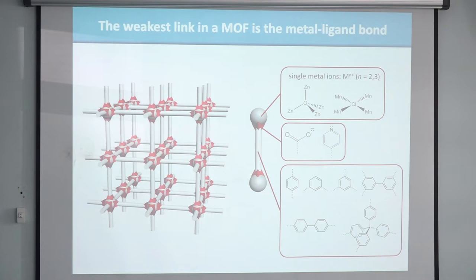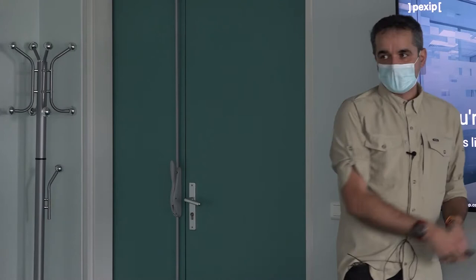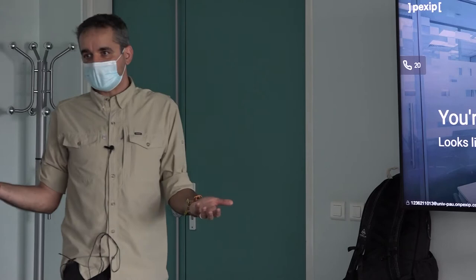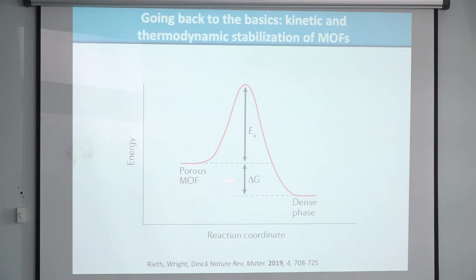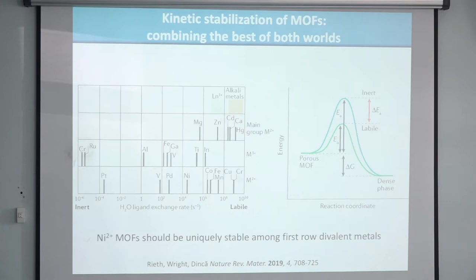If you take zinc and a carboxylic acid, that's not going to be very stable — it's literally a salt, so it'll dissolve in water. But you can ask a deeper question: any porous MOF is actually metastable relative to a dense phase, and this is true of zeolites too. There's nothing wrong with metastability — diamonds are metastable and nobody cares. What you care about is the height of the kinetic barrier, because you want to make them as kinetically stable as possible.